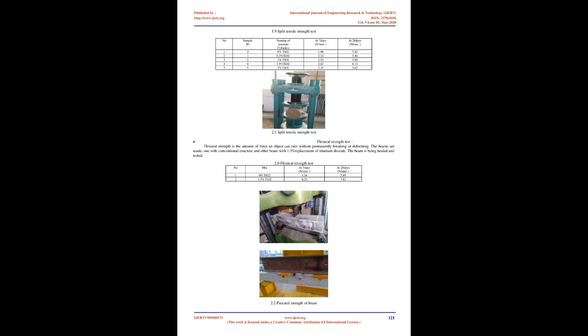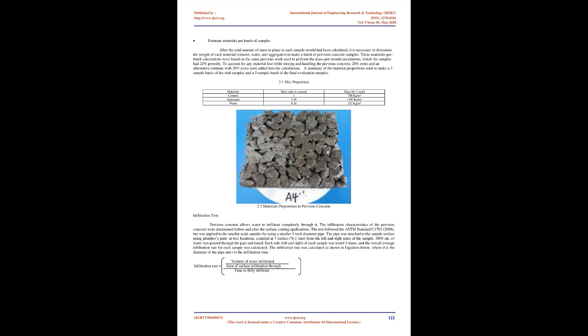2.1 Split tensile strength test. Flexural strength test. Flexural strength is the amount of force an object can take without permanently breaking or deforming. The beams are made, one with conventional concrete and the other beam with 1.5% replacement of titanium dioxide. The beam is cured and tested. 2.0 Flexural strength test. 2.2 Flexural strength of beam.